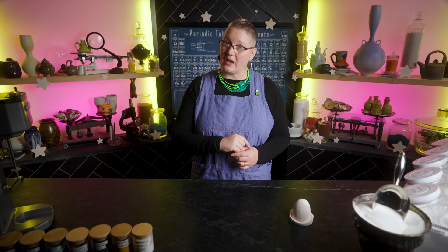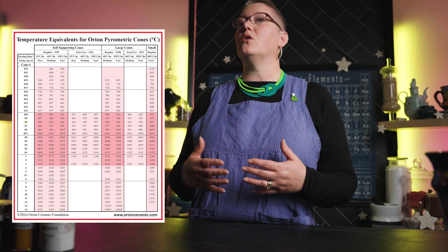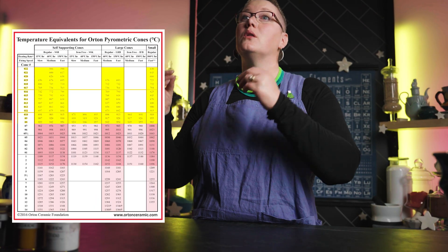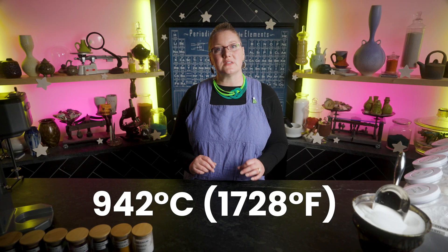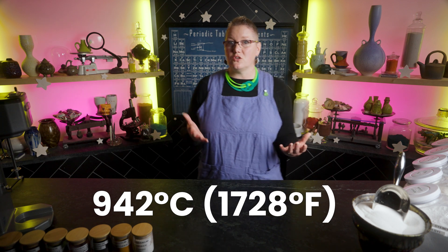The firing temperature. Yes, the powder can be fired in a kiln, but the temperature needs to be low — not low fire. Keep lowering your expectations even lower. For this glaze to work, you have to keep your firing temperature at cone 08 or lower. Cone 08 is 942 degrees Celsius, and that's a bigger complication than you may think.